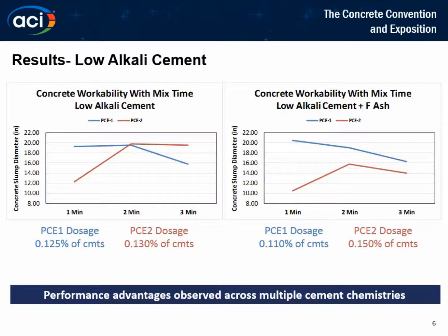Talking about transport, what I've seen is fast wetting mix, if you put it in a bucket, it gels quicker than cold pieces. I am not familiar with the gelling phenomena. We aren't seeing that rapid slump loss that you're discussing. Where we've seen that is more, if they're getting rapid slump loss, they're getting it from their general use PCE as well as their fast dispersing PCE. It's the mix design and the components in there that are causing that rapid slump loss more so than the impact of which PCE they're using.